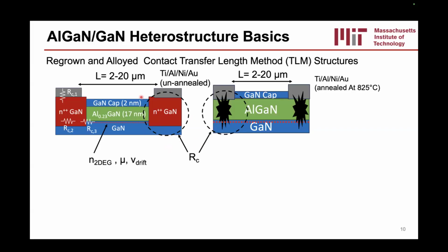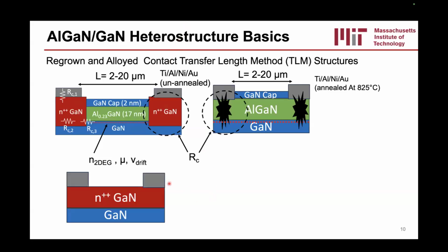By making these resistor or TLM structures, we can vary this length here and extract the sheet resistance and the contact resistance values, which I'll show in the next few slides. Additionally, we can also make structures that are just heavily doped GaN, and this helps us compartmentalize and extract some of the resistance components associated with the contacts. We can also make some Hall structures, and from this we can actually measure the density and the mobility directly, and we can do that as a function of temperature. So all of this in total allows us to measure the 2D density, the mobility, the drift velocity, and the contact resistance as a function of temperature, and understand what's limiting our device performance.